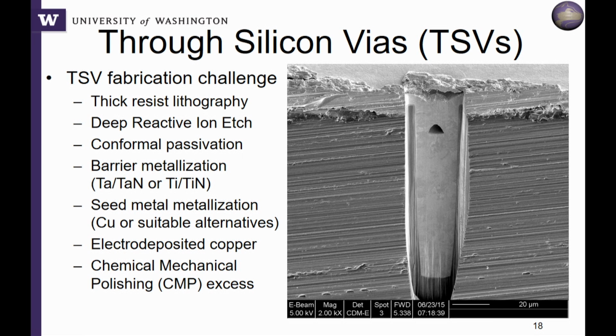You then have to isolate that hole from the substrate, from the metal. If you have a metal plug going through a piece of silicon—which is a semiconductor—there's a propensity for that metal to migrate into the silicon, and then you can start shorting to each other. So if you have two wires next to each other, there's a potential for them to short out through that substrate, or even just have crosstalk using high-frequency communications. So one of the limitations is we need to put some kind of isolation material.